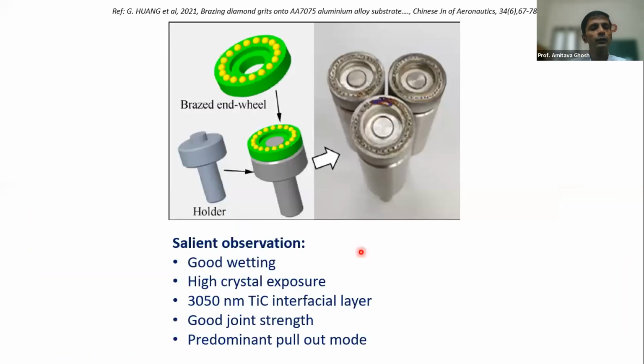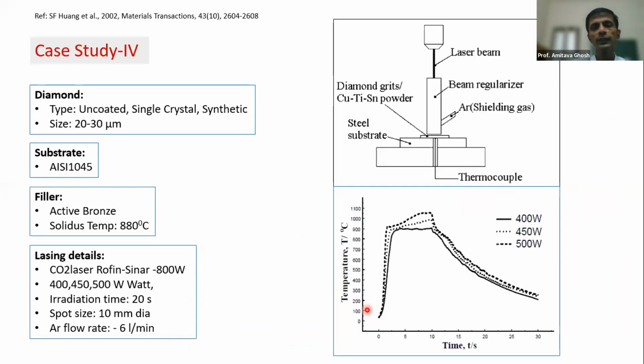The research group has presented that some of the tools they manufactured through this, and they observed that joint strength is pretty good, but the failure mode is majorly pull out. There is no breakage of the diamond as such. So these are a few results which indicate that the fastness of the laser process can be utilized much more productively for making such kinds of tools.